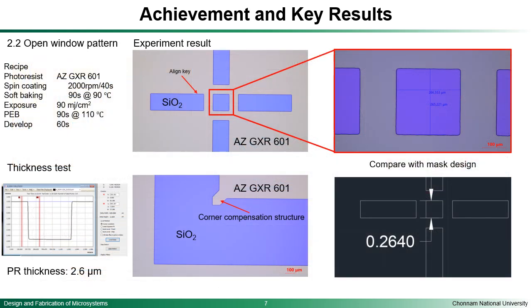And then we have already deposited the photoresist for the open window patterning by the mask 1. And we're using the positive photoresist of AZ GXR 601. And the result can be seen from the presentation slides, and also the tolerance with the mask design. It's in good terms of tolerance. And then for the thickness test, the PR thickness after we measure it by the surface profile is around 2.6 micrometer.